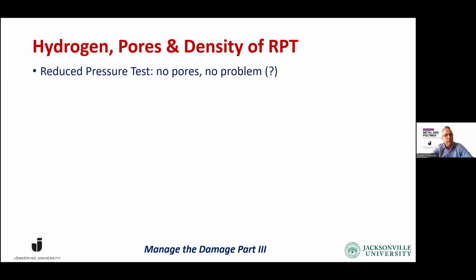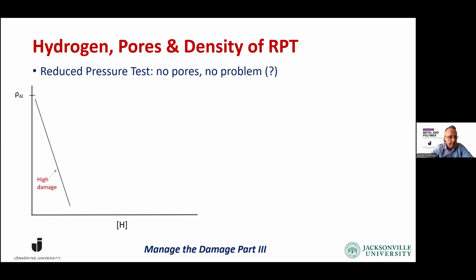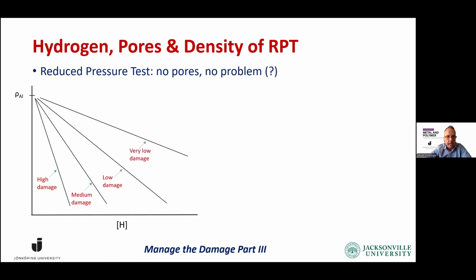So another technique that we use is the reduced pressure test. And if we were to have, maybe, a thought experiment, plot hydrogen content versus the density of the sample, our thinking is that if it's highly damaged, there is going to be a strong correlation between the hydrogen content and the density of the RPT specimen. And with decreasing damage, that correlation will be less strong. And when there's no damage, regardless of the hydrogen content, there would be no pores in our RPT samples.